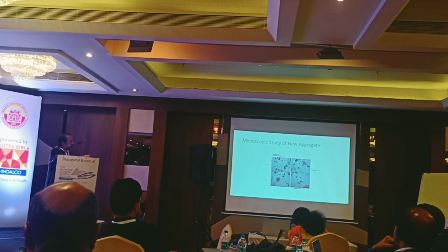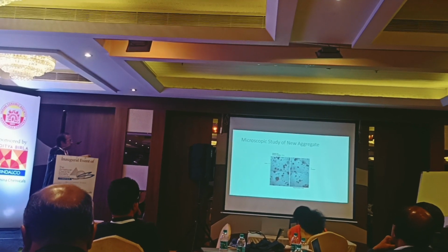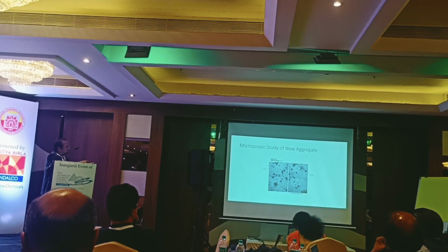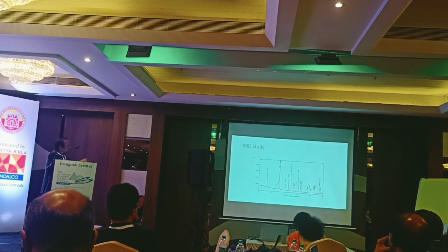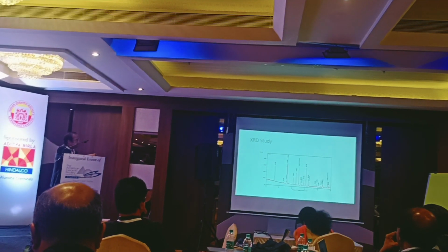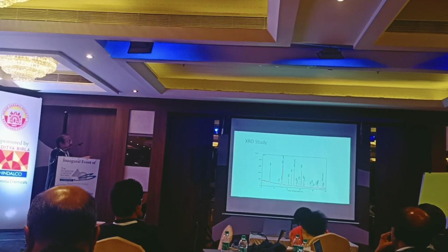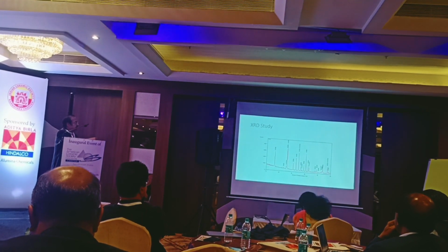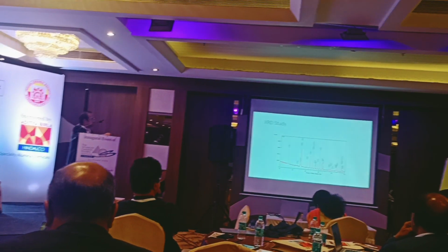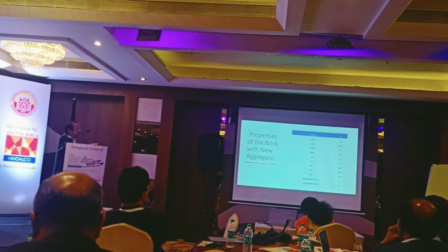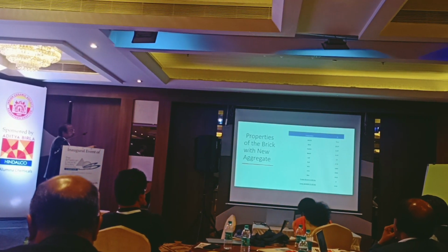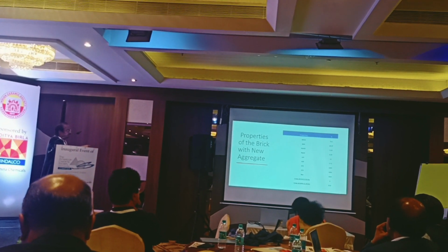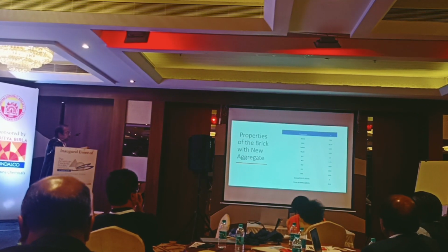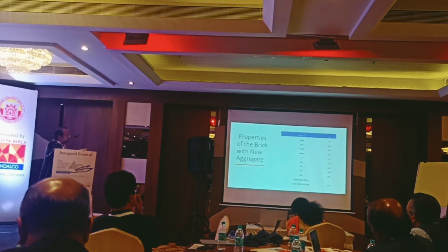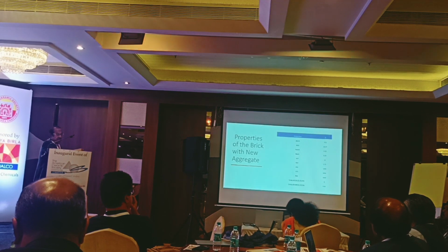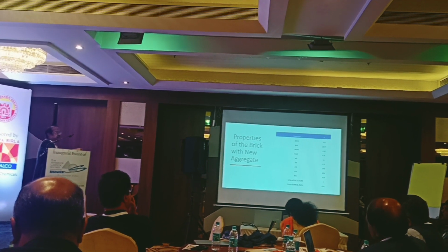So this is the microstructure we have developed for this. It has only mullite and corundum and nothing else. And this is the quantitative XRD study we have done to achieve the figure of 89% mullite phase and 11% corundum phase. And this is the brick we have developed. So here you can see that the creep at 1550 is 0 and at 1600 it is 0.02%. So this product is required very much for Indian industry.